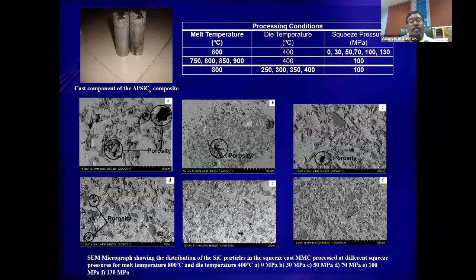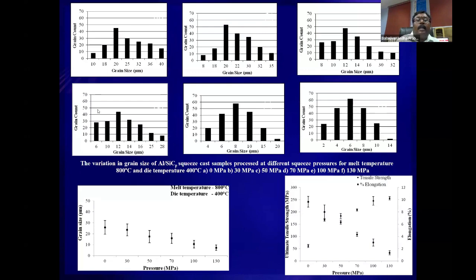And when it is solidifying, it's not trying to move out. So that means if you look at this pressure range 0 to 130, you could get some homogeneous distribution, and as a result, now we can also expect some grain size reduction, because you are creating a situation where the mode of heat transfer is conduction mode, with faster solidification. As a result, the matrix itself now has grain dimensions which are in a finer domain.